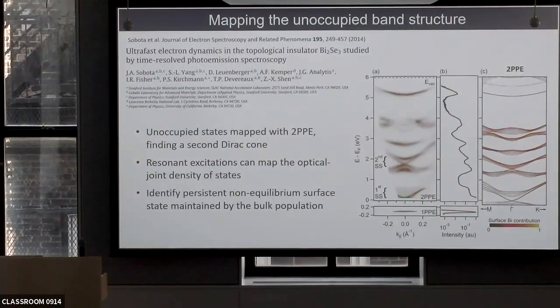dispersion of the solid. Something that you would be able to see if you did inverse photoemission, but you don't have this kind of resolution, or if you were able to dope the system all the way up there, but you can't really. And so by using this two-photon technique, again, one pump pulse exciting the sample and the second one probing at a certain delay, you can get a very detailed picture of the band dispersion above EF, to a point where you can see the topological surface state, the Dirac state here, but you also see the existence of a second one, which is usually not occupied in the pristine material.